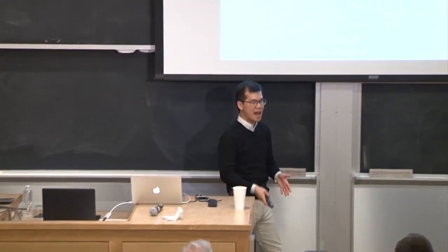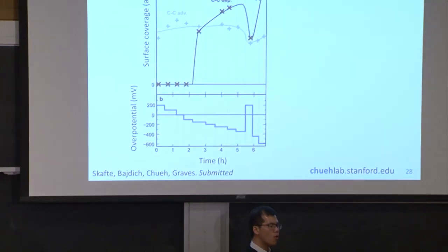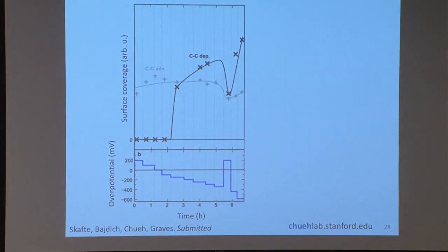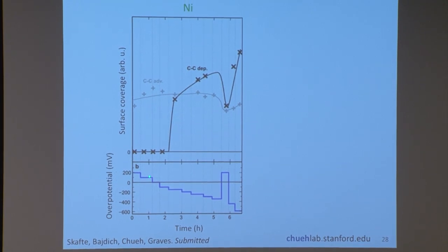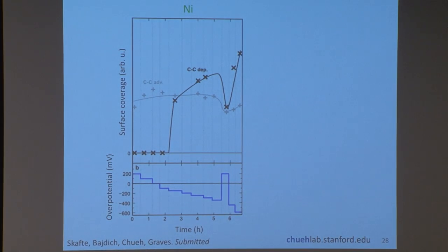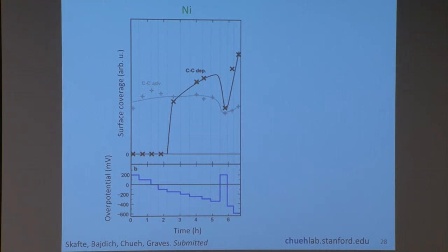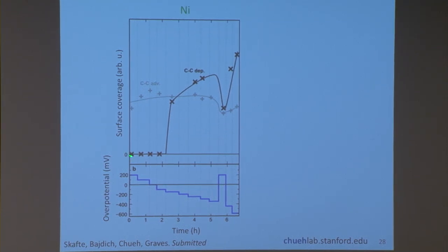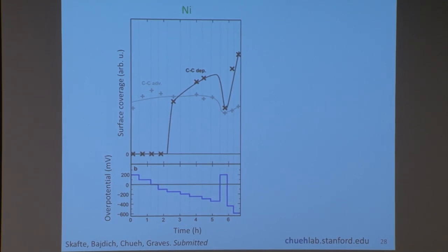So the great thing about being able to watch a reaction like this happen is record the dynamics. So we're able to follow as we apply a voltage to this electrolysis cell, as we step down the potential, we can actually monitor how the carbon is deposited in real time. So the x-axis here is time. So this is a great example of dynamical information. This is nickel, so all we see is basically carbon starts to deposit at the equilibrium threshold.